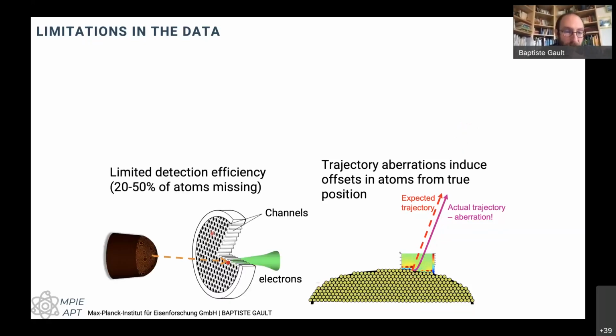And then the detector that we use doesn't detect all of the ions. Typically, they are making use of microchannel plates, which are basically a series of tiny photomultipliers. An ion coming into one of the tubes will trigger a cascade of electrons. We typically have 2 of those microchannel plates positioned one after the other, and it means that for one ion coming in, we typically detect about 1 million electrons, which is much easier to detect than a single ion.